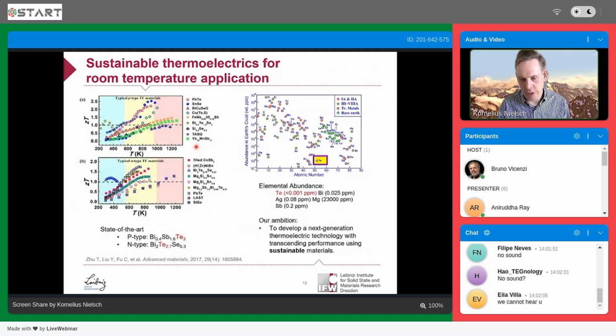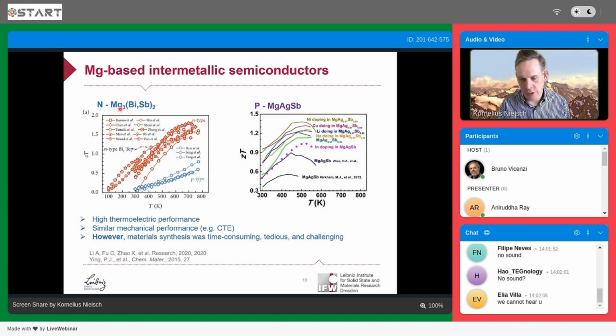So for this project, we looked especially for thermoelectric materials which can compete with bismuth telluride. You can see in both graphs, the upper one for the P-type material and the lower graph for the N-type material, there has been a lot of development in the last 10 to 20 years on high temperature materials for waste heat recovery, but there are very few competitors for bismuth telluride. The main competitor, which we have used here in the THERMOS project, is the magnesium bismuth antimonide, the N-type material.